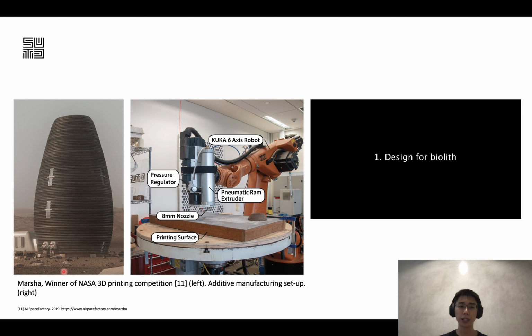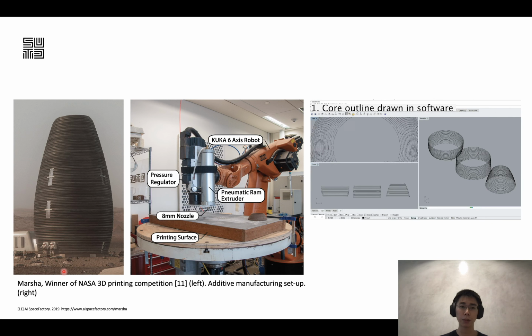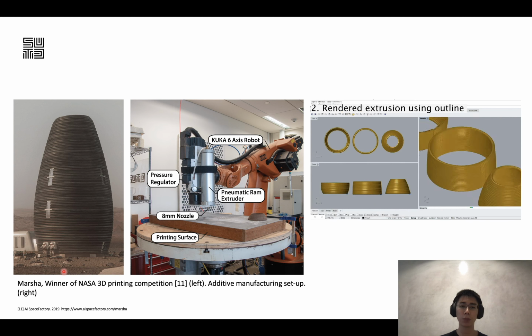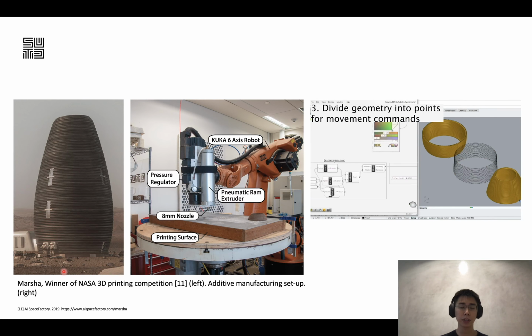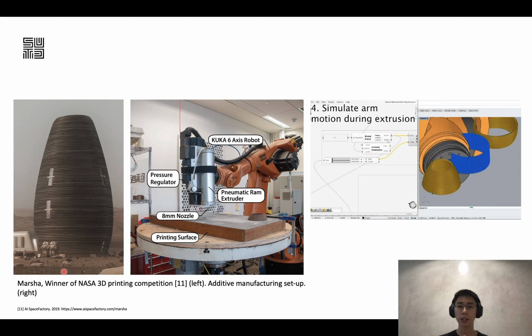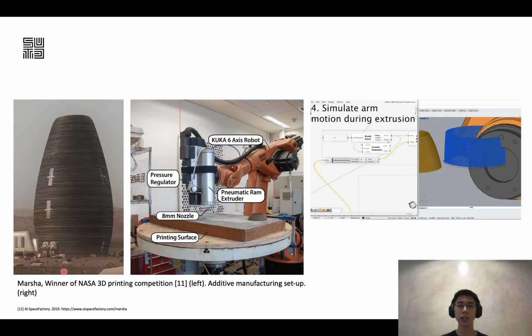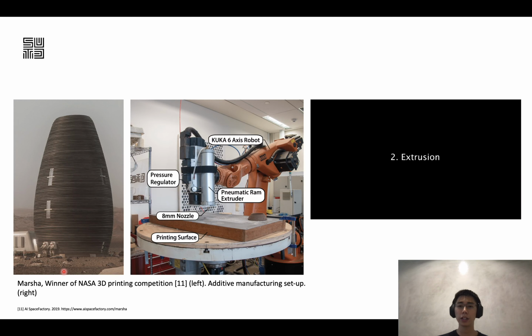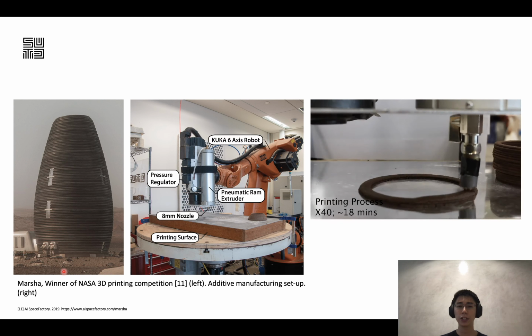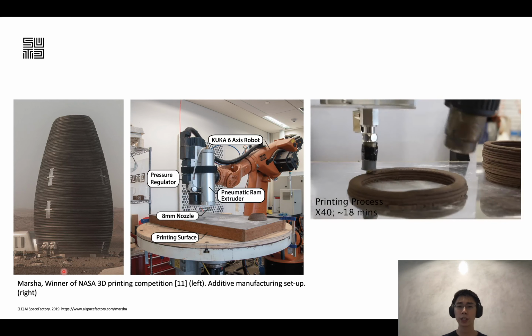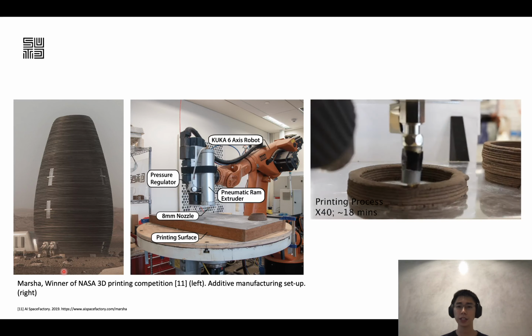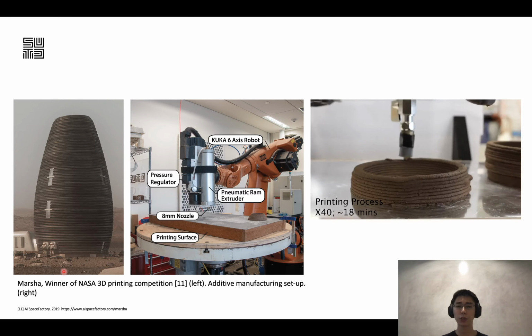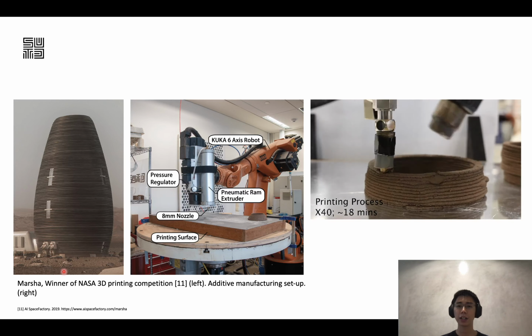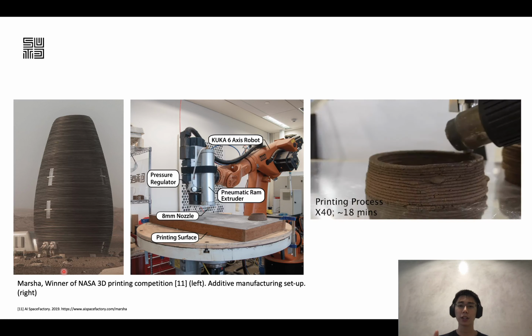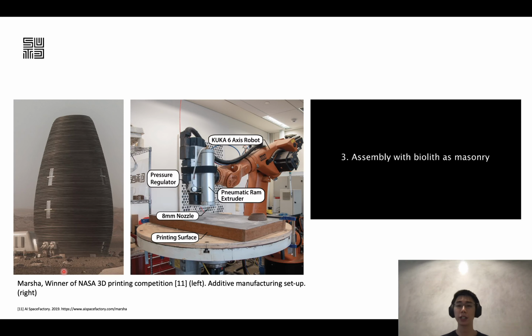Now, we actually demonstrate it in this application by replicating a scale model of the Martian habitat, which is the winner of a NASA 3D printing competition. So we basically mounted a pneumatic ram extruder on a robotic arm. We drew a scale model in Grasshopper, converted it into a toolpath for the robotic arm to follow, and then extruded out the material as you can see here. As it is being extruded, we accelerate the drying process using a hot air gun so that we can build more layers upon it.